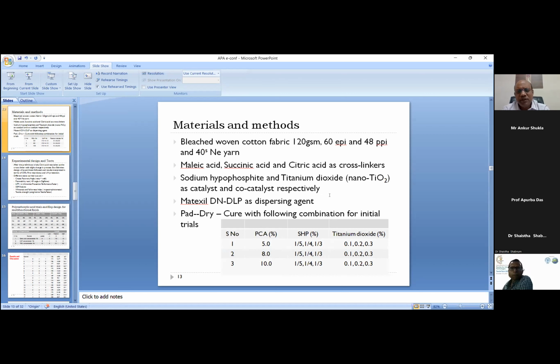And by pad dry cure application, as per the table given here, the different concentrations were tried. But the problem was, when these chemicals were tried, like maleic acid, succinic acid, and even citric acid, the level of anticrease was not very high. So later on, the work was narrowed down to citric acid, along with other parameters, and maleic acid and succinic acid were not subsequently used. But initial trials were taken with this, right?